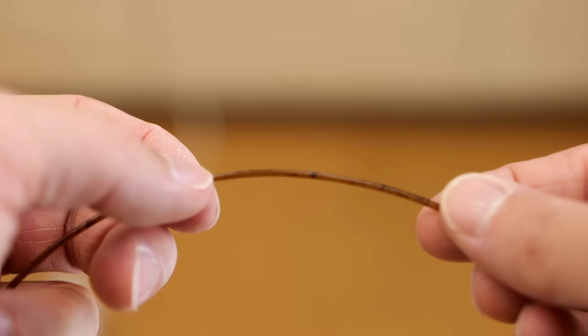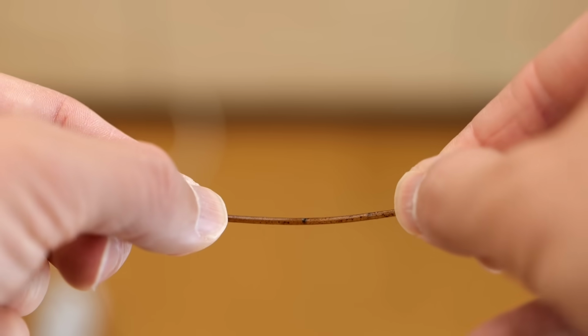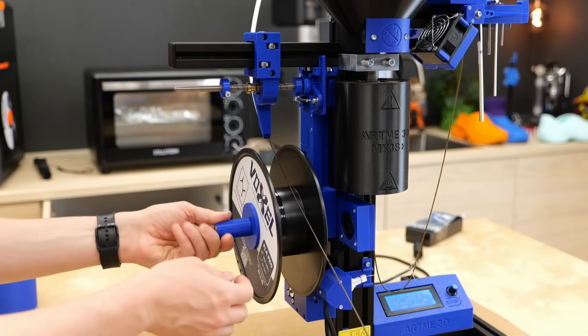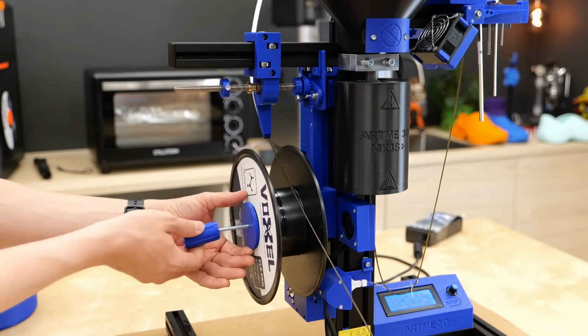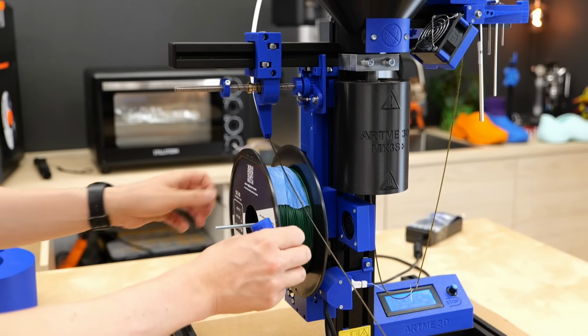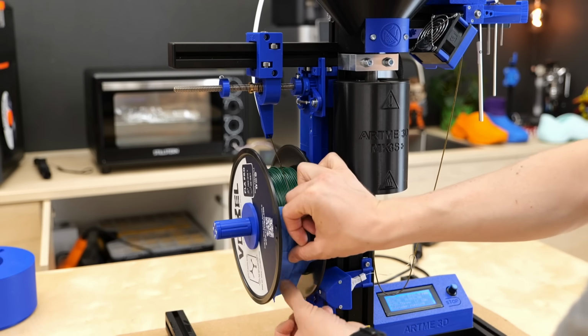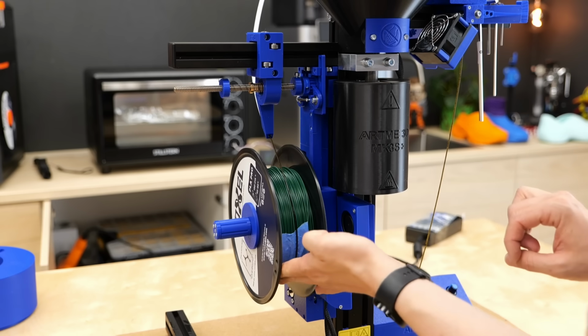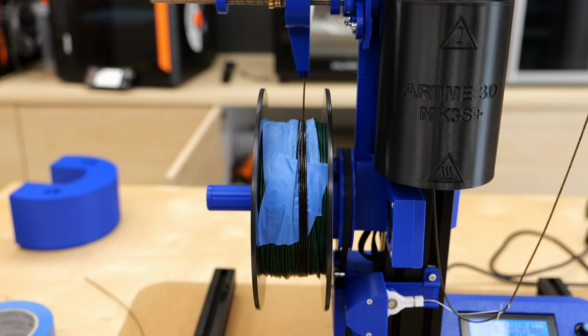I had the feeling that the material was super brittle, but at only 5% fibers added, that seemed a little strange. To at least spool a bit more material, I removed the empty spool and added a spool that was half full. That way the bend radius of the filament was smaller and should reduce the risk of breaking. And that seemed to do the trick.